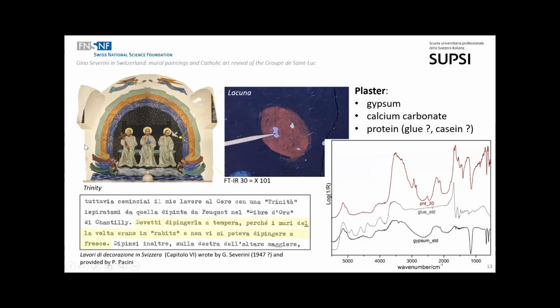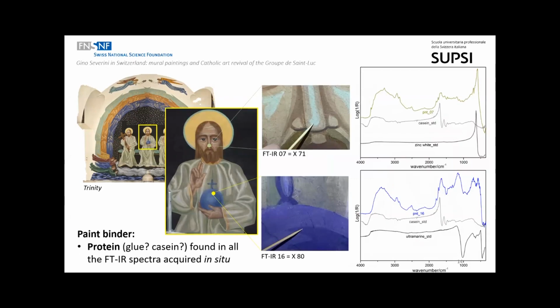Severini wrote that in this wall of the apse, he found a gypsum plaster, and for this reason he used a secco technique, probably using an organic binder like a protein material. The presence of a protein material also emerged in all the FTIR spectra acquired for the different painted areas, confirming obviously the evidence of this material, used probably as a paint binder.